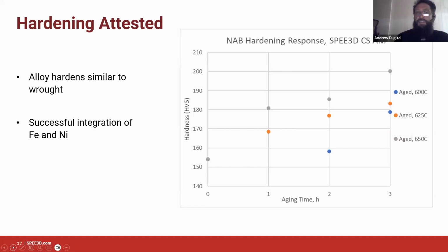Okay, so the next step is to look at, can we get the thing to harden? And in a lot of ways, that's the acid test for have you really homogenized the alloy successfully? Because obviously it's not going to behave itself through the hardening process if all of the elements are not participating in that reaction. And often we do have the thing where we convince ourselves that we've succeeded, and then the hardening doesn't quite go the way that we want, and we realize that we have to work a bit harder on homogenization. But these are the results we got after a little bit of work in NAB.